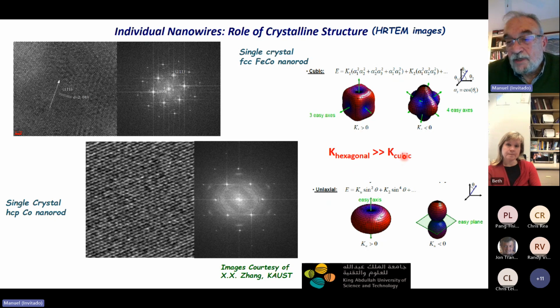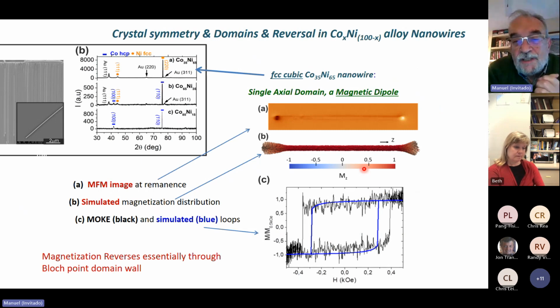So in the case of cubic crystals, the shape anisotropy is typically larger than the magnetocrystalline anisotropy, but not in the case of hexagonal crystals, where we have to consider the fight between the hexagonal magnetocrystalline anisotropy and the shape anisotropy. Then let me show you the result for individual nanowires in the cobalt-nickel series with different nickel content. If we have a wire with large nickel content, cobalt 35, nickel 65, we know that it has a cubic structure. In the magnetic force microscopy image at remanence, we have an ideal magnetic dipole with two charges, black and white, at the very ends, causing some stray fields near the ends of the nanowires.